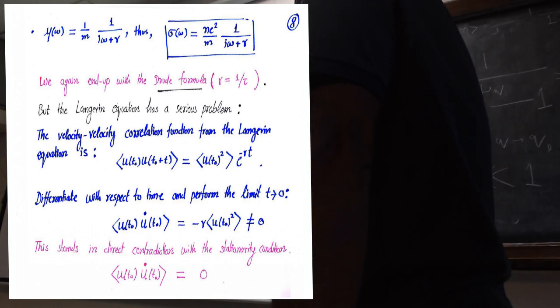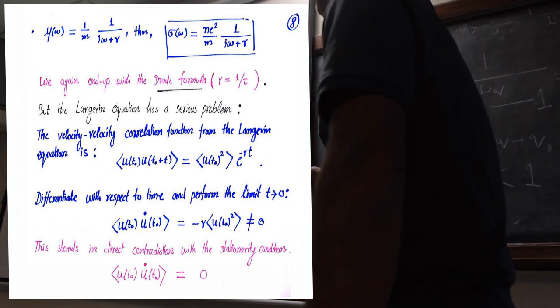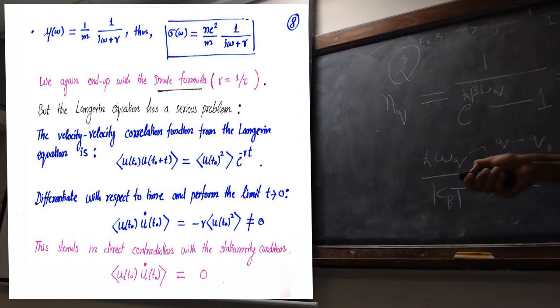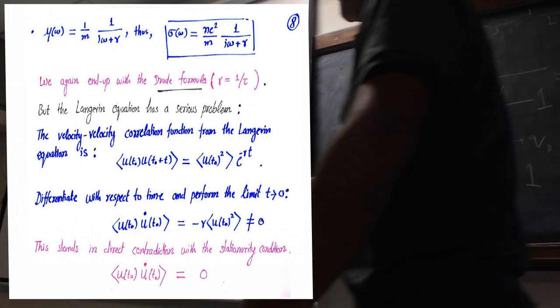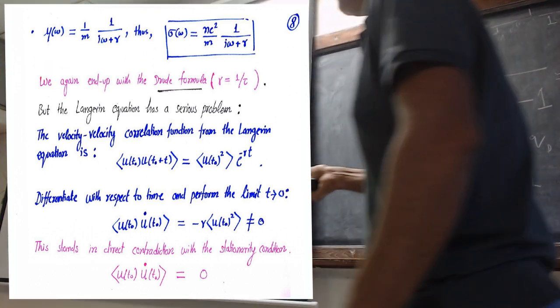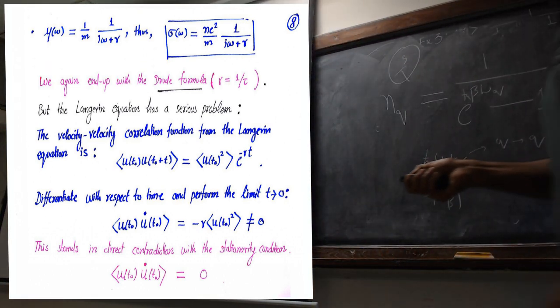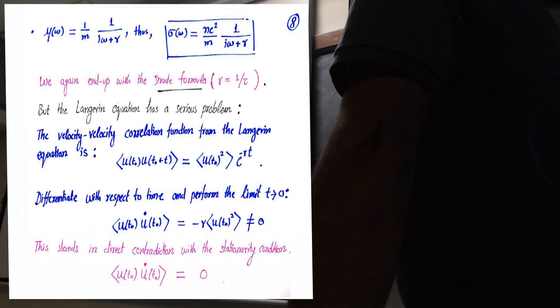Now, to see that there is a problem with the Drude formula obtained from the Langevin equation, let us look at the equation from which the Drude formula is derived. The equation is the Langevin equation. It is very well known from the studies of non-equilibrium statistical mechanics. It's not a new result. It was known to people like Kubo, Van Kampen, in the 1950s and 60s, that this suffers from a very big defect.